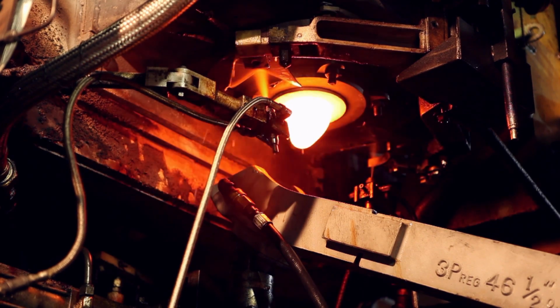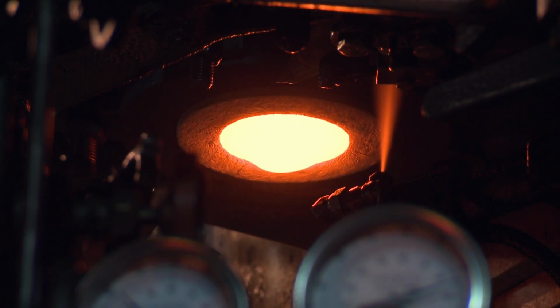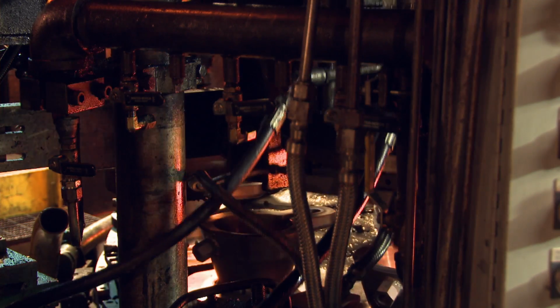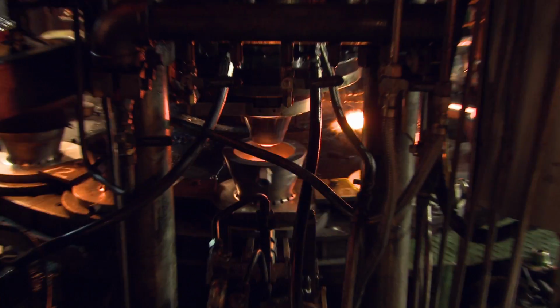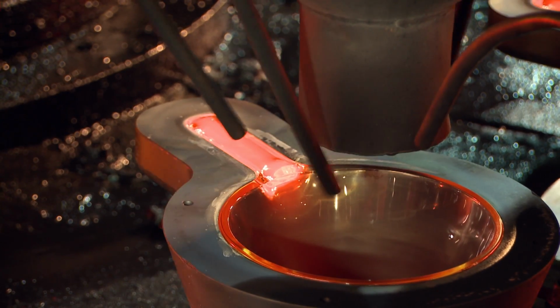At that point, the glass flows out of a bowl. Imagine just a hole in the bottom of a bucket. We cut it into what we call gobs, and the gobs fall down a chute into the mold itself. The press holds 16 molds, which rotate on a carousel, capturing the falling gobs of molten glass. The glass is then pressed into molds and cooled slowly with compressed air.